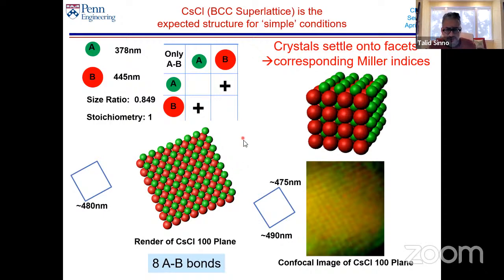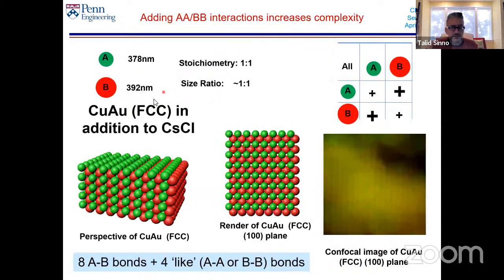If you change things a little bit, so now we go to a size ratio closer to 1 to 1, and instead of a pure AB system we have a system where some AA and some BB interactions are allowed by mixing some of the A and B strands on the respective particles, and you let that system evolve, now you get a very different configuration.